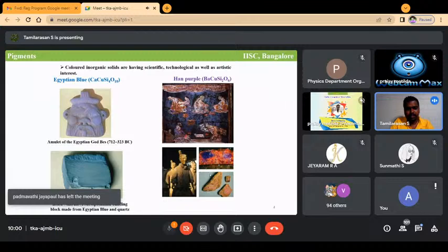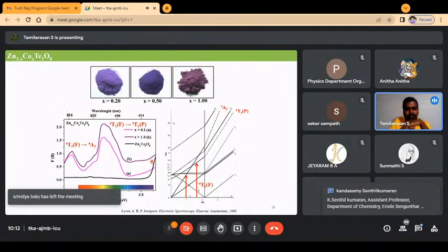So that's a cool pigment. And then we wanted to further investigate what we would get in a distorted octahedral environment. Octahedra is a very common coordination geometry we would encounter in most of the materials, but still, if it is distorted, what would be the color of common transition divalent metal atoms? And we proceeded with doping cobalt in zinc position and got this nice purple, violet, purple, blue.